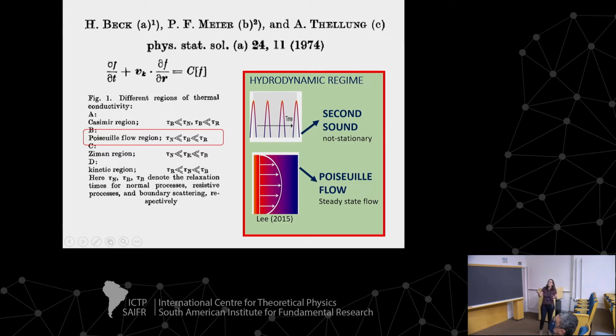What happened is that, I will not enter into details, but in phonon transport we can associate some scattering time with respect to different scattering mechanisms. So if we call here tau B the boundary, phonons are limited by the physical boundary of the material. Tau N are the normal ones, I will say something more about that, and tau resistive. So tau N are scattering events that preserve momentum, and tau R that degrade momentum. A manifestation, the experimental evidence for the hydrodynamic regime, is the observation of the second sound or the Poiseuille flow. So Poiseuille flow is observed in thermal conductivity.